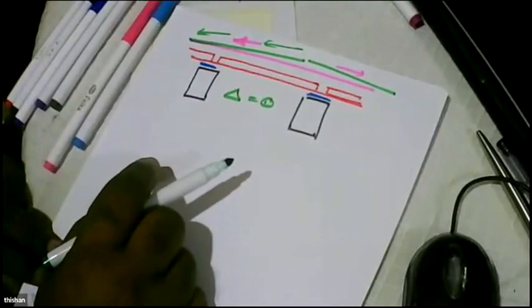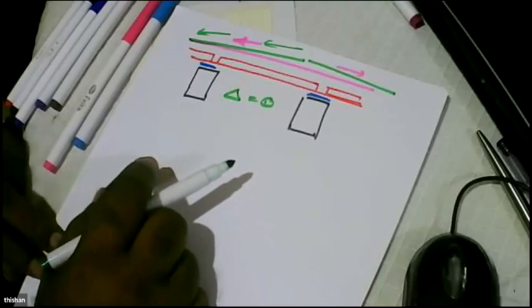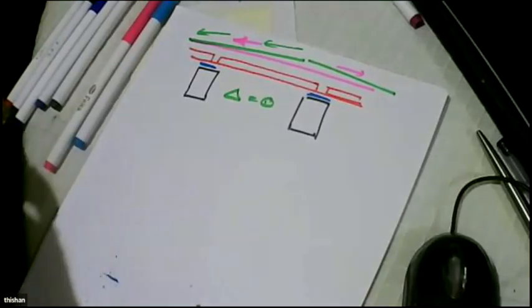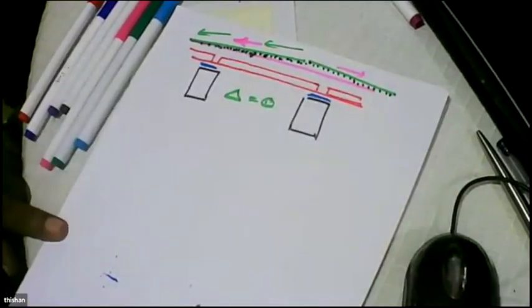Because most of the time you'll find that due to creep and shrinkage, slabs sag, and this sag causes water to stagnate. When the water stagnates, all the problems will come, and waterproofing problems will be there for that reason. So what we can do is embed chips so that they will not wear out. Though the cement can be washed away, the chips will not. So we create chips here.